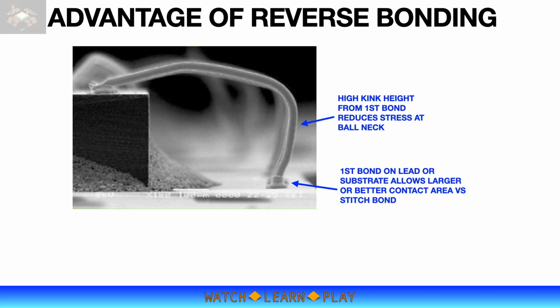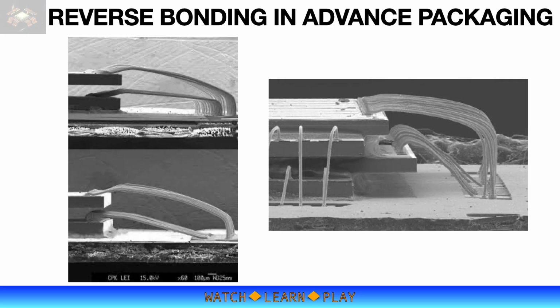There are some advantages in using reverse bonding method. It allows a high kink height on top of the ball, which reduces bending stress at ball neck. Also, the bonded ball on the lead or substrate allows greater and better contact area that improves bonding strength, that is particularly weaker with stitch bonded onto the lead or substrate. This is very important in SiP or hybrid packaging, where substrate pads are not the typical soft gold-coated surface. Here are some examples of reverse bonding in advanced packaging applications.